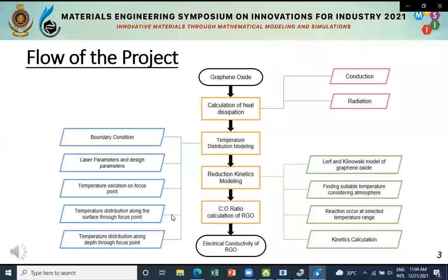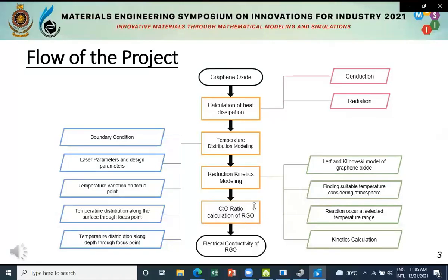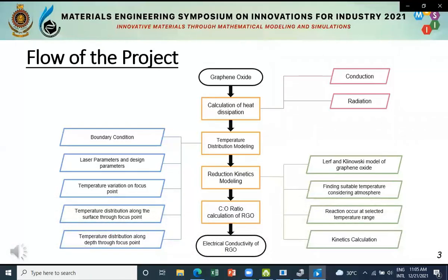As a first step, we calculated heat dissipation of graphene oxide films considering conduction and radiation. Then we modeled temperature distribution by considering boundary conditions, laser parameters and design parameters. Then we modeled temperature variation at the focus point, temperature distribution along the surface through the focus point, and temperature distribution along depth through the focus point. With the results of temperature distribution modeling, we modeled reduction kinetics. There, we used the Lerf and Klinowski model of graphene oxide, and we found a suitable temperature range, and the reaction that occurred in that temperature range for kinetics calculations.